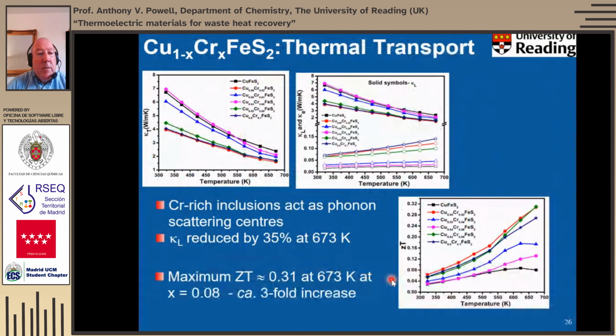However, these inclusions seem to have a very beneficial effect on thermal transport because they act as phonon scattering centers, and they reduce the lattice contribution of the thermal conductivity. So that's this set of curves here. This is the lattice contribution, this is the electronic contribution, this is the total thermal conductivity. It reduces the lattice contribution to thermal conductivity by about 35% at 673 Kelvin. And that allows us to increase our figure of merit by a factor of almost 3 compared to the end member copper iron sulfide. And we can get up to, at the moment, 0.31 at 673 Kelvin.